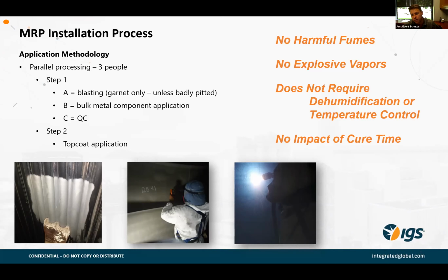And then blasting is followed by a QC function to make sure there are no holidays in the blasting and the white metal finish is achieved. And then step B is where the HVTS gets applied. Directly after the HVTS application is followed by another QC using elcometers, such as in that center picture there, to verify that you've got a thickness of 8 to 12 mils. So depending on the application, there's a specific range which we need to stay within. And once step one, A, B, and C is done, so once you've blasted, applied the metal component, and did your QC, we also do a coating thickness map of the entire scope area. And once that's done and satisfactory, we apply that top coat that we mentioned earlier.